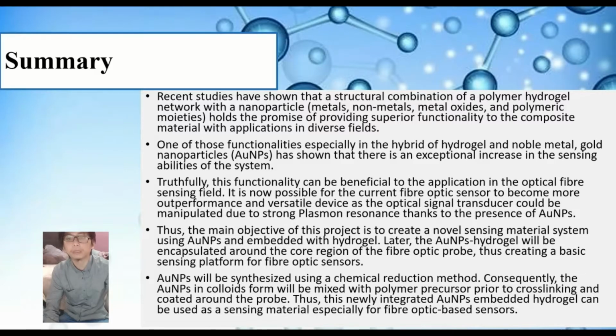It is now possible for the current fiber optic sensor to become a more performant and versatile device, as the optical signal transducer could be manipulated due to the strong plasmon resonance thanks to the presence of our nanoparticles. Thus, the main objective of this project is to create a novel sensing material system using our nanoparticles embedded into hydrogels. Later, the nanoparticle hydrogels will be encapsulated around the core region of the fiber optic probe, thus creating a basic sensing platform for fiber optic sensors.